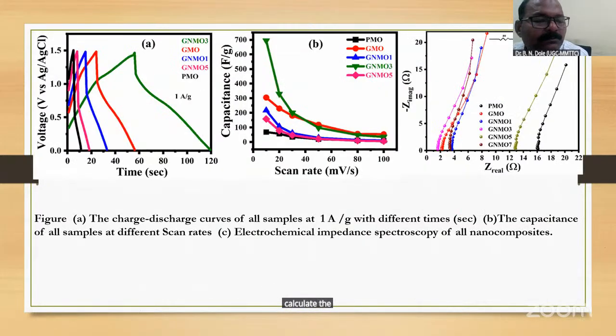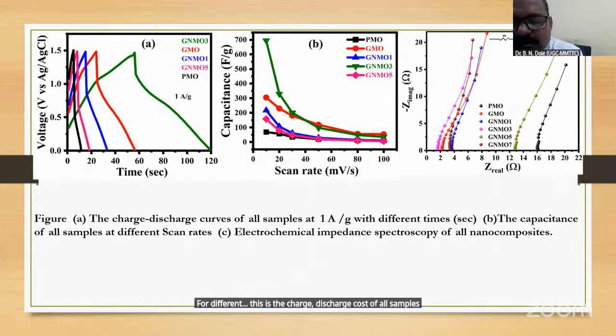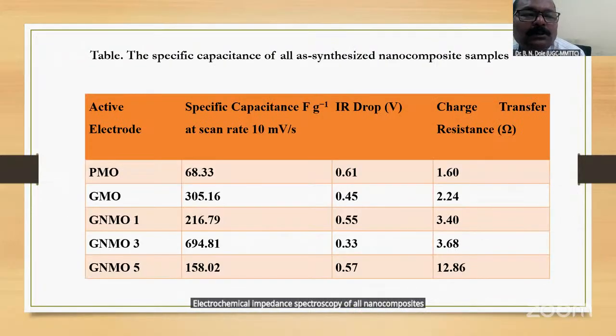Calculate the capacitance for different scan rates. This is the charge discharge curves of all samples at 1 ampere per gram with different times. The capacitance of all samples at different scan rates, electrochemical impedance spectroscopy of all nanocomposites. The specific capacitance of all as synthesized nanocomposite samples. Active electrode specific capacitance in farad per gram at scan rate 10 millivolt per second. This is charge transfer resistance also calculated, and see here that charge transfer resistance enhanced.